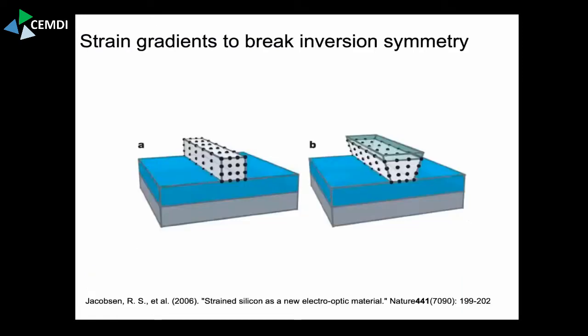Now, this is an early example from 2006, a Nature paper where they used silicon, and they actually grew a little bit of extra, I think it was germanium, on the top of the silicon, getting this wedge shape, and this strain gradient and the broken inversion symmetry in this cross section essentially give rise to optical birefringence, electro-optic effects, and so on. So this was an early example of strain engineering to invoke new properties in materials.